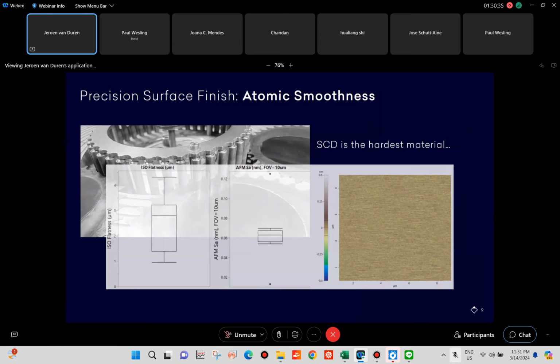Regarding smoothness, Joana touched on that. Diamond is the hardest material on the planet. So can you get it to atomic level smoothness? Yes, we can. We do this day in, day out. On the right, you see a 10 by 10 micron area as measured by AFM. You can see it's extremely smooth. You see in the middle a box plot for smoothness as measured with AFM, and you see it's just a few angstroms. What's also important for various applications is flatness and total thickness variation. And as you can see, it's just a few microns. So, very tight specifications, as people are used to in the semiconductor industry.